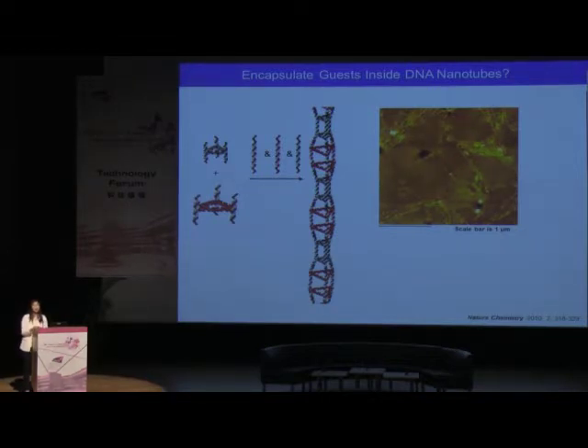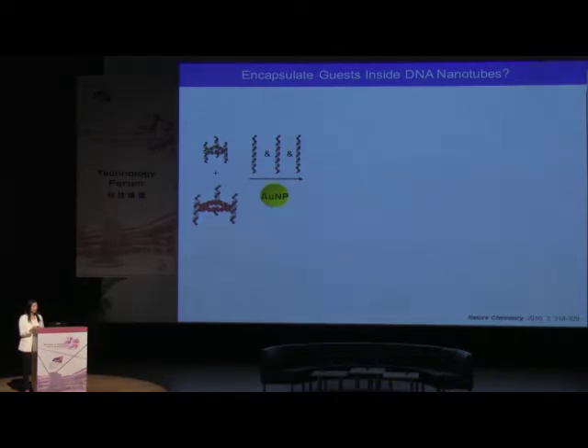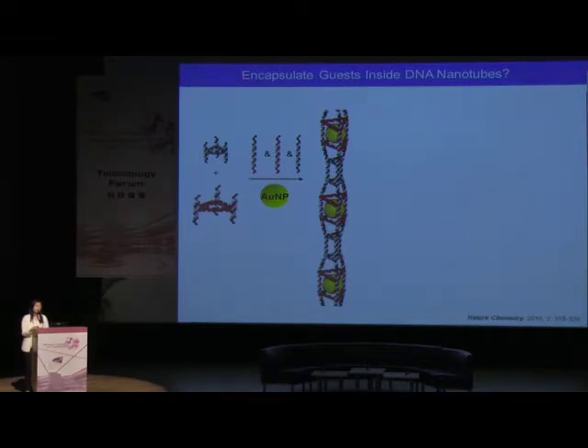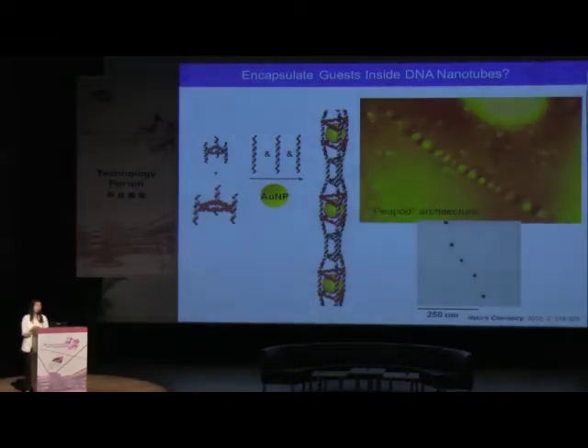And to study the encapsulation inside the nanotube, first of all, we assume that the guest molecule should not have the affinity to the DNA so that they do not stick to the DNA unless there is encapsulation. And to demonstrate the idea, we are taking a gold nanoparticle, which is 15 nanometer diameter, with citrate coated, which is negatively charged on the surface, and our DNA is also negatively charged. So we assume that they should not come together unless there is encapsulation, which means that the gold nanoparticle should only sit in the large capsule with a regular distance. And from the AFM and TEM study, we also confirmed the spacing and also the architecture from this kind of nanotube.